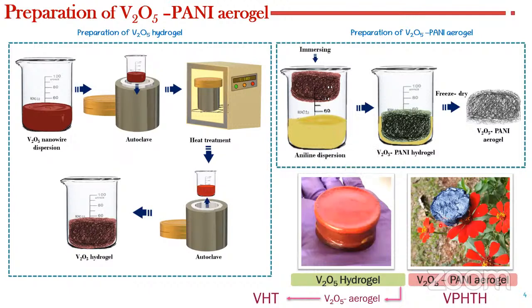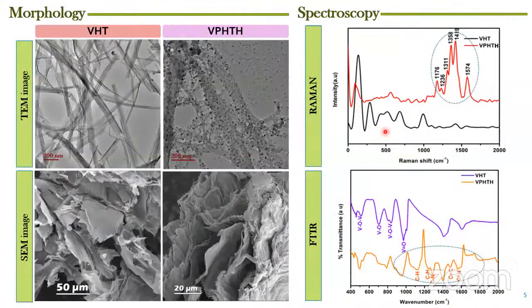The pure V2O5 hydrogel was directly freeze-dried to get V2O5 aerogel, just for comparison studies. It was coded as VHT, and the composite material was coded as VPHTH. The TEM image shows the ultra long nanowire morphology of VHT. In the composite sample, you can see the polymer wraps these nanowires, and so these nanowires become conducting due to the presence of the conducting polymer polyaniline.